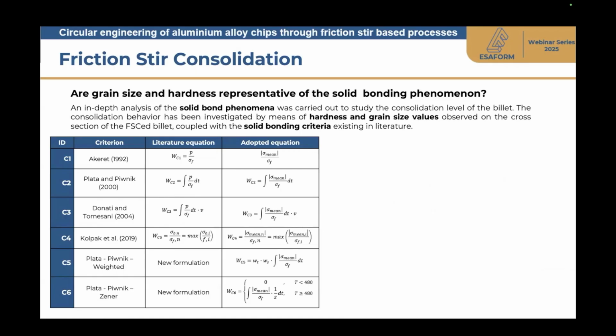And also, the idea was to apply a huge number of criteria of bonding phenomena proposed in literature, and also some new formulations given by the combination of proper material parameters and material information obtained both from the experiments and from the numerical model. Well, in terms of bonding, the most popular and famous criterion is probably Plata and Piwnik, proposed in 2000, in which it is considered the integral of the history, so of the local pressure and of the material flow.